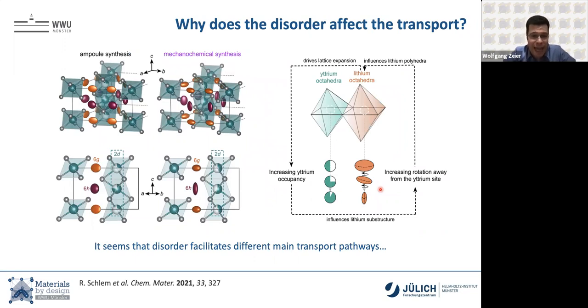What we think is happening, and this slide we need to take with a grain of salt, because here I'm pointing at anisotropic thermal displacement parameters obtained by neutron diffraction from powder. And the caveat here is the powder. But what we do see is that when you go from your ampule synthesized material to your ball milled material, the one lithium position starts pointing more upwards for an in-plane ionic conductivity.